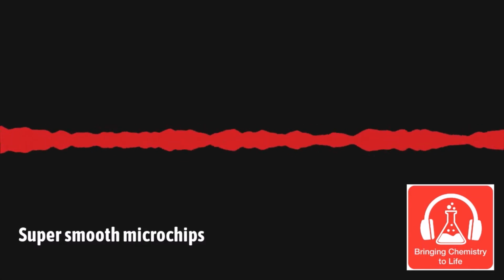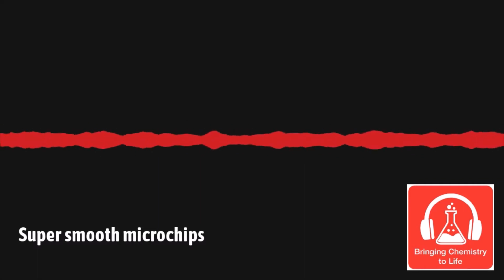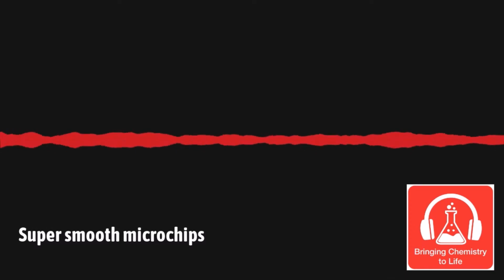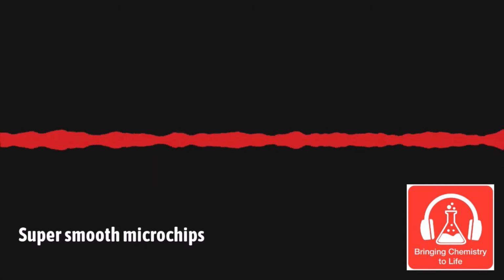So CMP is used multiple times in the manufacturing process of a single microchip. There could be even several passes on one single layer, right? It all depends on which layer you are in the integrated circuit. So in addition to removing excess film materials, CMP is also used to buff the surface to remove surface defectivity and also to correct the topography as well.